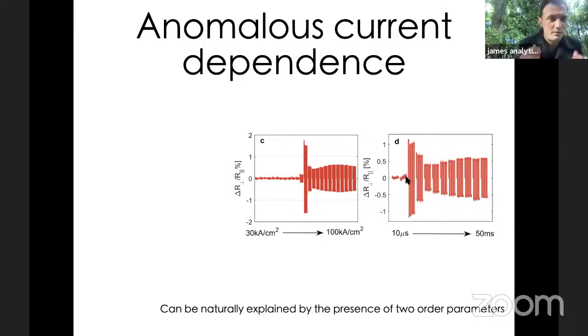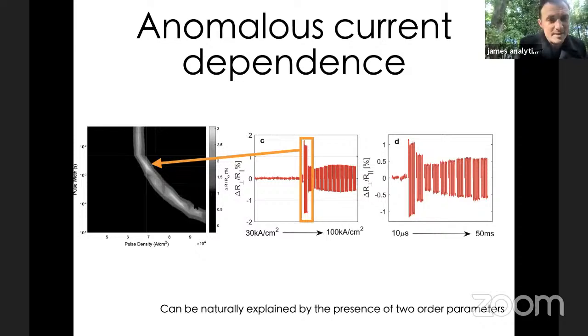So fixing the current density and changing the duration of the pulse, you see this large increase and then a sudden decrease and then kind of a saturation. This is not natural in the typical antiferromagnetic switching perspective. You have a threshold current, and then once you're over that threshold current, you can always rotate. Here, there's some preferred threshold current, and then every one after that is suppressed. And you can actually plot this in a color plot, a contour plot, and you can see that this threshold current really kind of follows a semicircle.